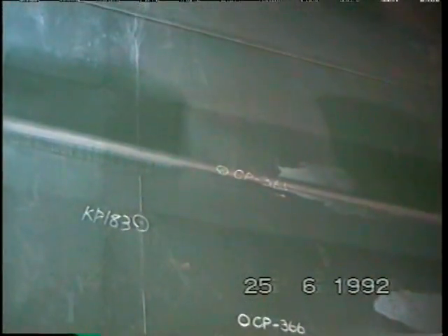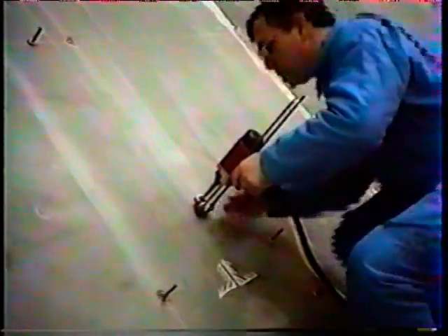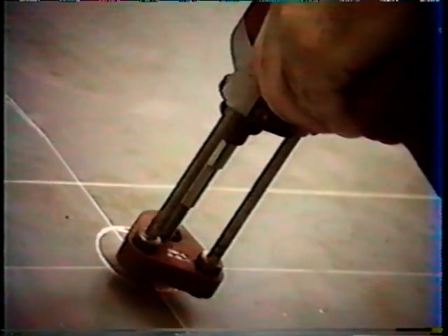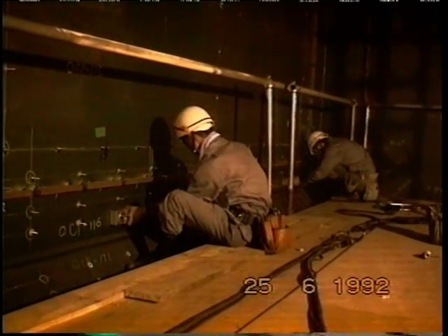Next, the inside surface of the tank and its flatness defects are precisely measured. Square anchoring bars are welded along the edge of each bulkhead. After tracing the axes, the threaded studs are welded to intersections on the flat part in a 3 meter by 1 meter grid. The studs are automatically welded with a welding gun. The intermediary studs are automatically positioned and welded with templates between two previously positioned studs.